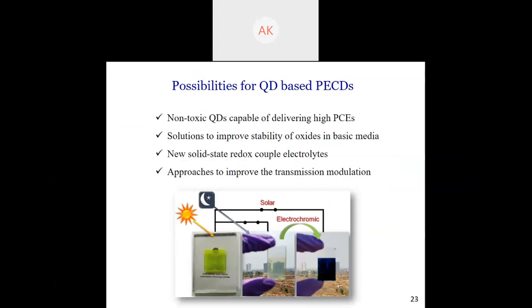I have used cadmium sulfide, which I can in no way call non-toxic, but you can use quantum dots which are cadmium or lead free, that is copper indium sulfide, copper indium selenide, and still get high power conversion efficiency. There has to be some solution to improve the stability of oxide in basic media. Here I have used one, that is the SiO2 layer. New solid state redox couple electrolytes can also be an alternative to be used.